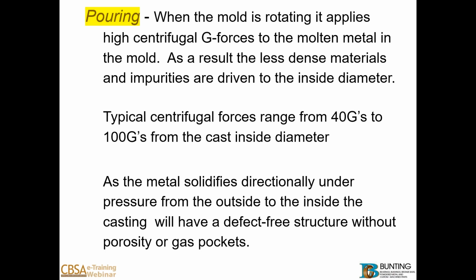So a lot of times, if you look at a casting after it's been cast, the ID is not as visually pleasing as the OD, typically. Typically speaking, centrifugal forces range from 40 Gs to 100 Gs from the cast inside diameter. That's where we tend to do our calculation from. And again, horizontal generally runs faster than a vertical casting, because of the vertical nature versus horizontal nature.